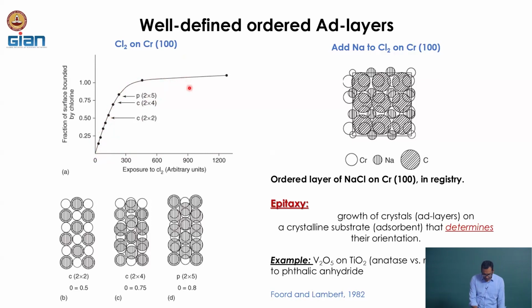And a couple of examples as a demonstration are shown here. If I have a surface coverage of 0.5, then the surface mesh structure of the chlorine is a C2 cross 2 type of geometry, whereas for a surface coverage of 0.8, it is going to be a P2 cross 5 geometry.